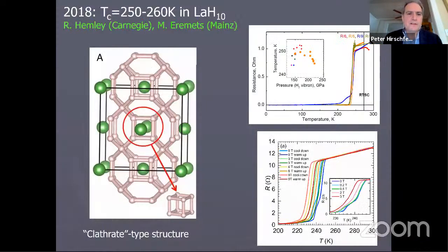But there are some further developments. A couple of years later, my slide is blocked here, so I can't see the year, but maybe 2 years ago, 3 years ago, Russ Hemley and Mikhail Eremets, both around the same time, came up with this clathrate-type structure where the green atoms are lanthanum and the little pink ones are hydrogen. There's a kind of a cage structure of hydrogen, which has high energy phonon modes, which give rise to even higher critical temperatures around 200, up to about 250 onset temperature. 200, I think, yeah, maybe even 250, 260 in this material.